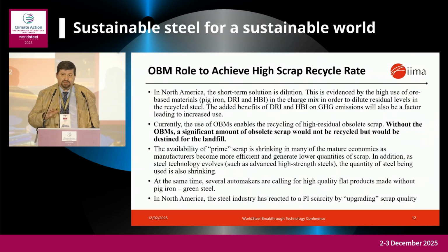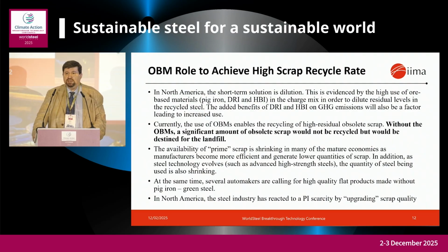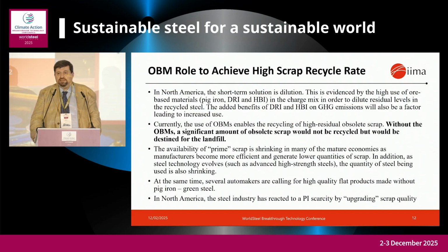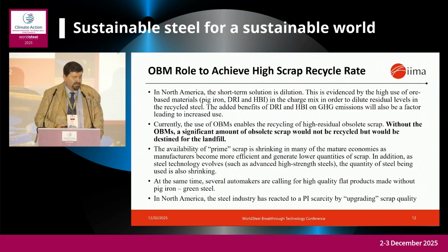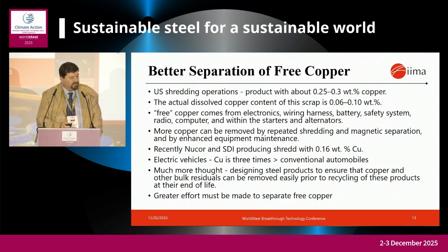So again, this whole thing of how much OBMs do we need? If we can clean the scrap up and remove a lot of the free copper that's not actually in the steel itself, then our dependence on OBMs is reduced. It doesn't go away. In the future, we're all going to be using OBMs in an EAF. The other thing we're fighting is that prime scrap availability is shrinking. The quality of prime scrap will actually go down as blast furnaces get phased out, because blast furnaces are producing automotive steel at like an 03 copper. From an EAF, we produce it at like an 08 copper. So as we transition to more EAF-based production, the copper content, even in the prime scrap, goes up a little. So these are all things that we have to be aware of.